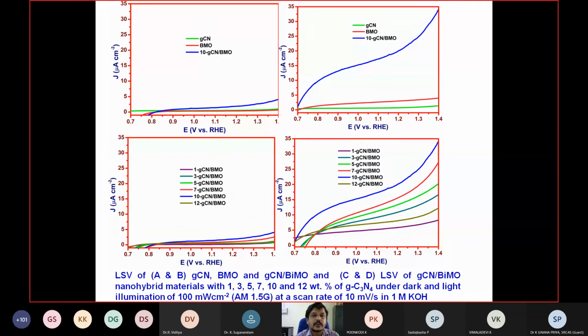Then we have done the photoelectrochemical water splitting. For this, first we recorded the LSV, linear sweep voltammogram, for the control experiments like graphitic carbon nitride, bismuth molybdate, and the best material. In the absence of light, you can see there is no current. Likewise, when we switch on the light, those materials show enhanced photocurrent. That means the materials are undergoing charge separation that produces hydrogen. As a result, the photocurrent density increased.